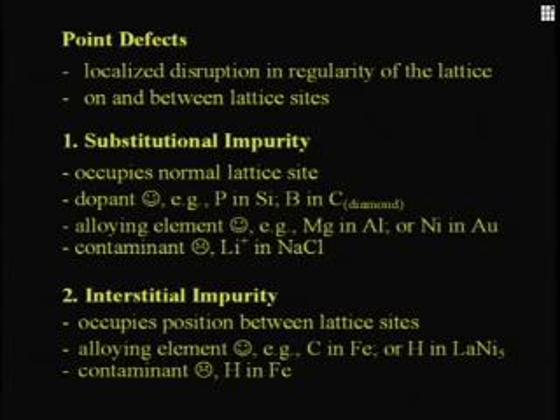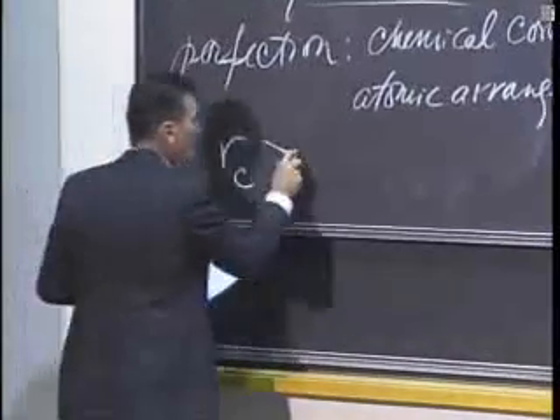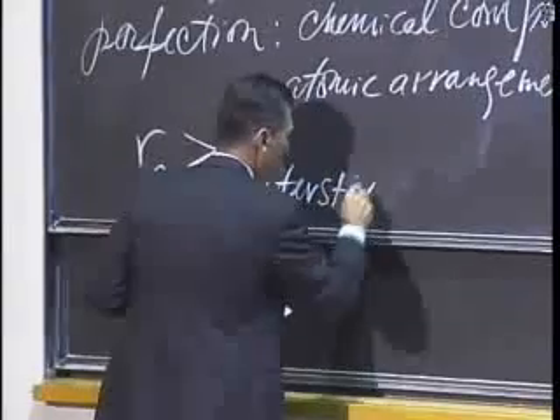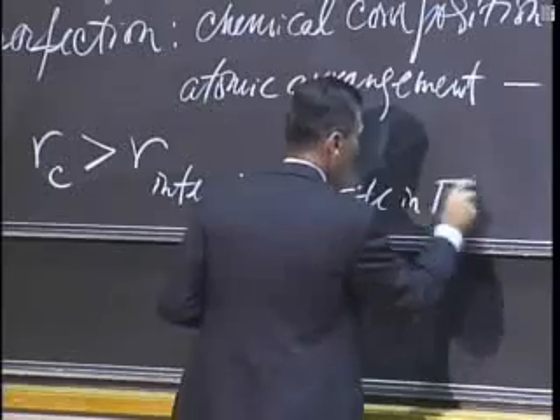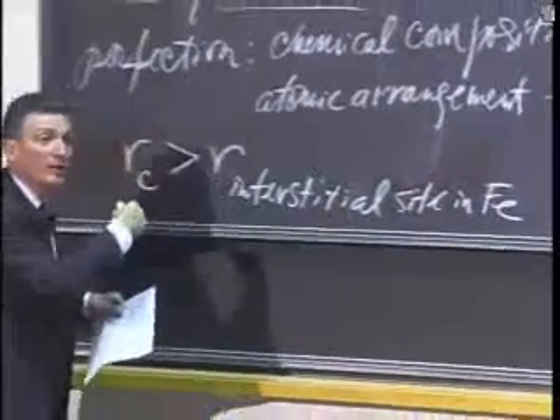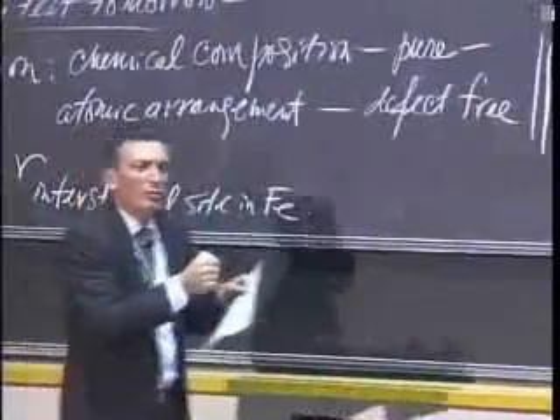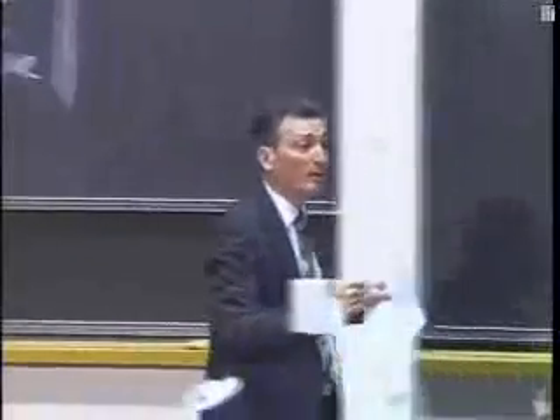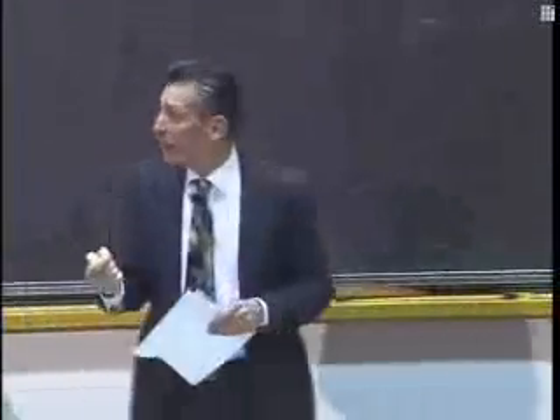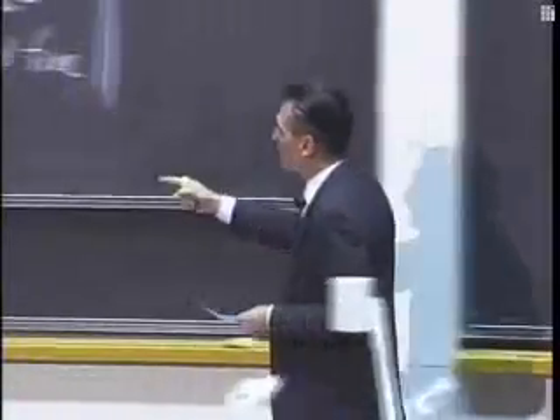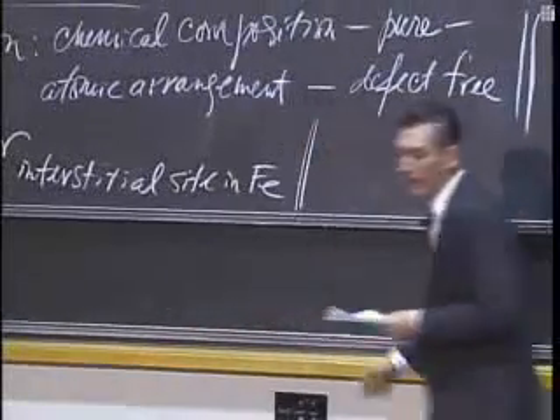And the interesting thing about carbon in iron is that the radius of the carbon atom is actually greater than the radius of the interstitial site in iron. So therefore, when the carbon goes into that interstitial site, it actually distorts the lattice. It presses back on the parent iron lattice, and through this distortion strengthens the material.